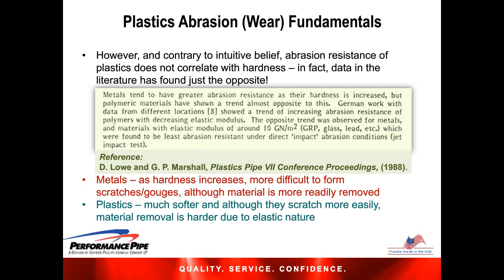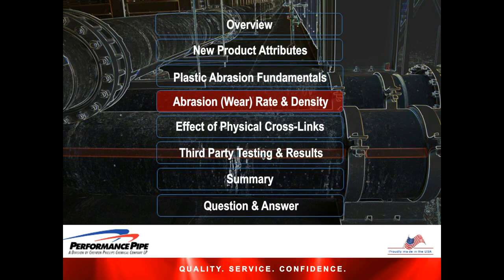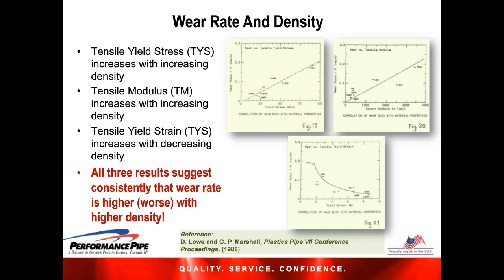So we look now at a little bit of data from the literature to support this notion that abrasion wear in plastics is really quite different from that in metals. We begin by looking at some data from the reference article, again by Lowe and Marshall, where these three different plots are shown. The left one here is wear rate as a function of tensile yield strength, wear rate as a function of tensile modulus, and then the wear rate as a function of the tensile yield strain.